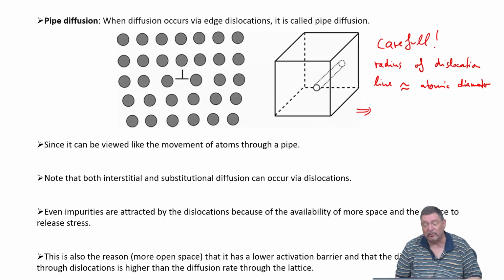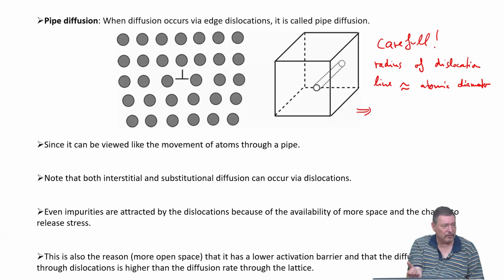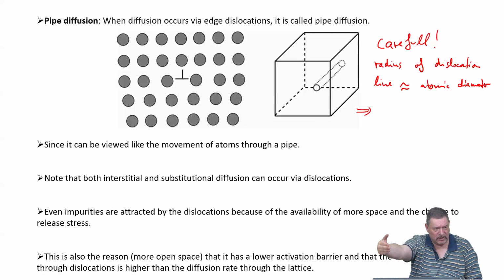This has an effect on the properties of the material, certainly, because you, for example, get preferential segregation of several of the atoms along dislocation pipes, and then you get something like these effects where you have dislocation motion prevented first by the segregating atoms, and only if a certain critical stress is overcome, then the dislocation can basically move away from the cloud of solute atoms, of impurity atoms, and then sometimes they move again to the new position of the dislocation.